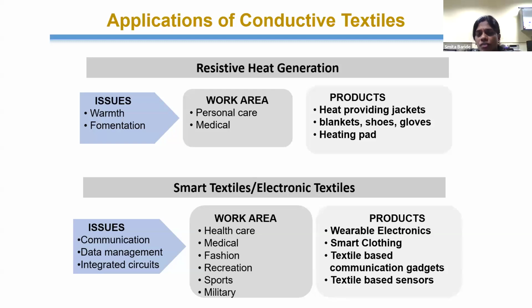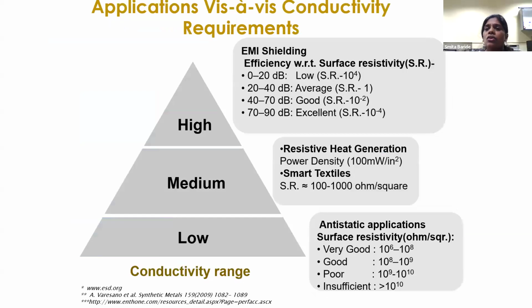I will show you one of our prototypes of how we are able to use that conducting material as a gas sensor. So as I said, depending on the conductivity, this conductive textile has a wide range of applications. Very highly conducting fabric, as I said, can be used for EMI shielding. And the resistivity range there is basically from 0.01 ohms per square to 10 ohms per square.